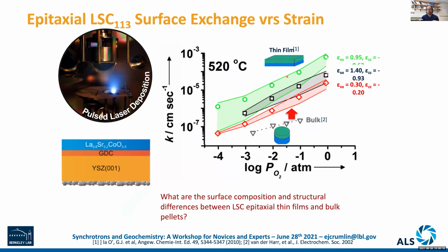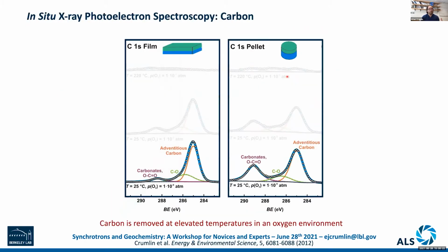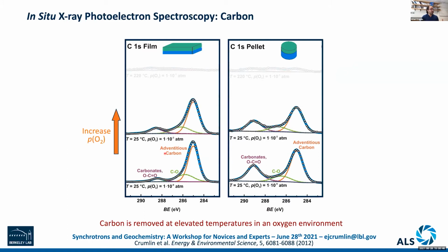So looking at this for really the first time in an ambient pressure environment, we brought this into an ambient pressure XPS, and we started off by collecting XPS. This is the traditional XPS spectra you would see from a largely lab-based system. You'd see the carbon 1s, since carbon is on everything that you naturally bring in. This is not really a surprise, but what's interesting is now we can change the environment. So we're going to add a gas environment, we're going to add oxygen. We're going to go from this UHV environment to a 10⁻³ atmosphere environment, so very high pressures of oxygen in comparison to what was there before.